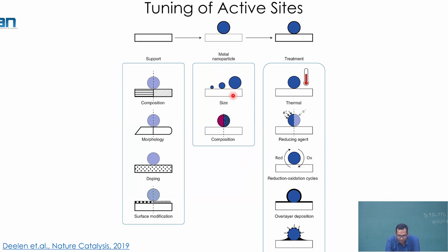Only 10% of the initial activity was lost over 40 hours as compared to the one which was only treated in hydrogen for 60 minutes. The deactivation happened at least 35% as compared to the fresh catalyst.